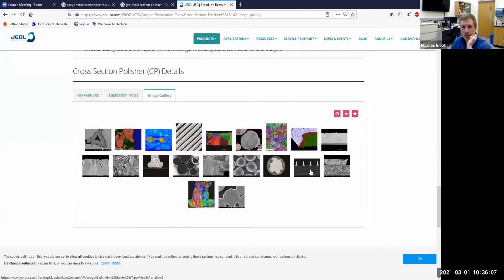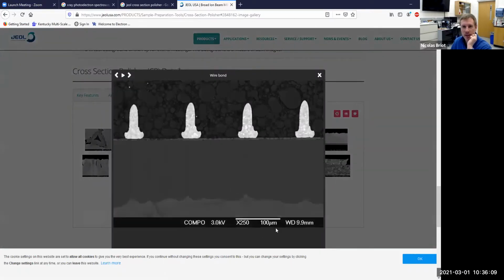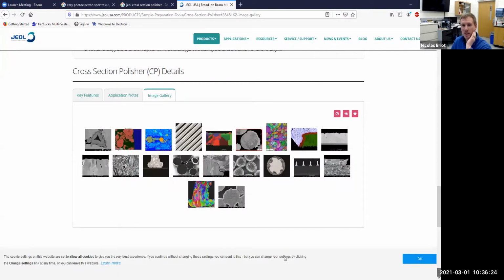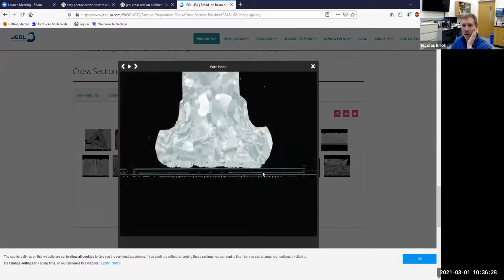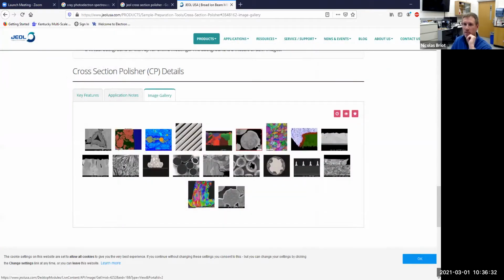I want to show high. Yeah, there we go. You see 100 microns, so you can make cuts that are millimeter wide, millimeter deep. Really keep a nice surface and everything. And instead of using gallium ions in the focused ion beam SEM like I'm doing right now, it's argon ions, kind of like what I mentioned in the XPS, but it's very soft, so it doesn't make too much damage. And you can really make some large cuts.